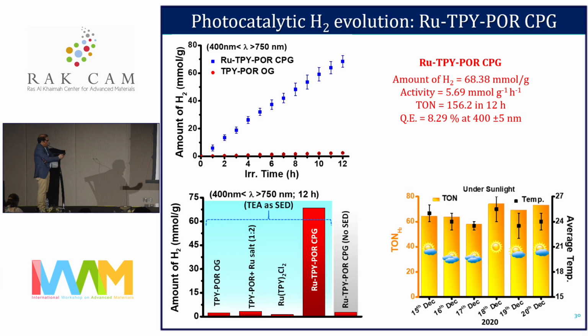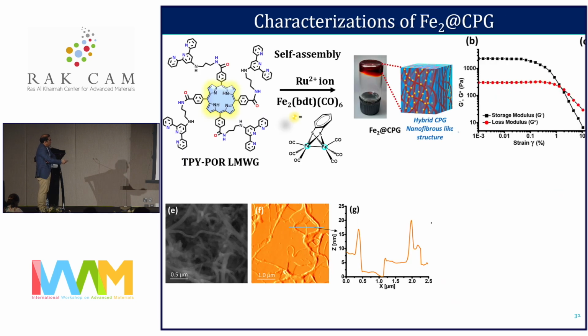We also tested this under sunlight with different control experiments. The ruthenium-porphyrin system is much more active in the presence of the TEA, triethylamine, and it is also equally active in sunlight. So then we prepared a simple molecule which mimics the hydrogenase enzyme, the di-iron cluster.